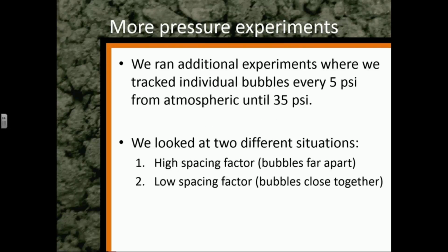So let's do some more experiments. We're going to do some additional experiments where we actually track how individual bubbles change every 5 psi. We're going to do that from atmospheric pressure up until 35 psi. And we're going to look at two different situations. One, when the bubbles have a high spacing factor, the bubbles are far apart from one another. And then two, when bubbles have a low spacing factor, or bubbles are close together.